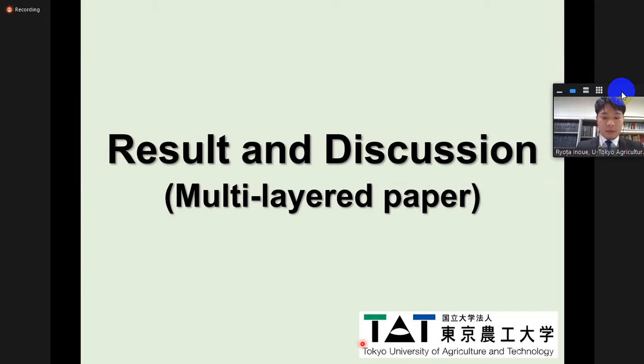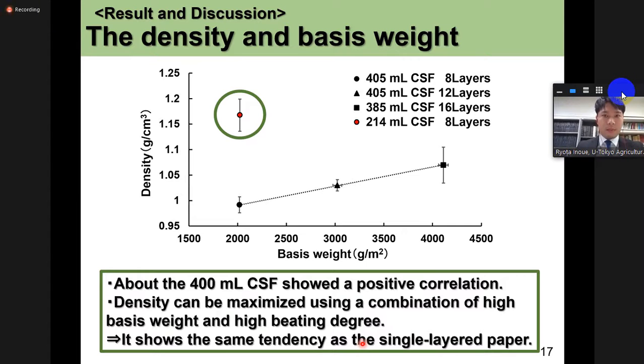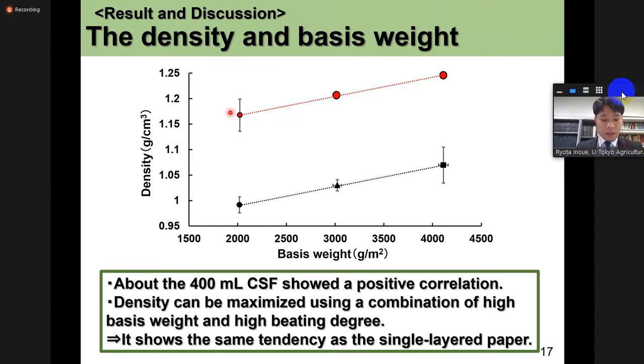Now, I'd like to move on to the topic of multi-layered paper. This figure shows the relationship between the density and the base weight of multi-layered paper. The red point indicates high beating degree. There is a positive correlation between the density and the base weight at the freeness of about 400 milliliters CSF. The red point shows that the density can be maximized using a combination of high base weight and a high beating degree. You can notice that it shows the same tendency as the single-layered paper. Therefore, it can be expected that the red point in the further high base weight region also will show a positive correlation.